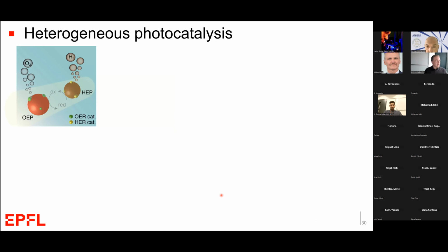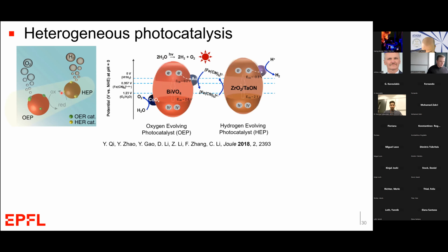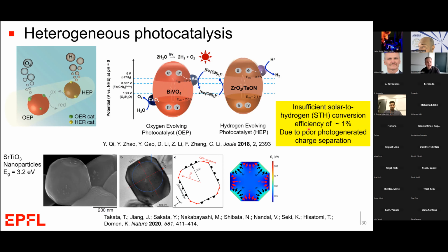And if I switch gears a little bit and talk for a second about that photocatalyst type approach, as I mentioned before, I'm really inspired by this approach, given its simplicity, right? Simply taking a nanoparticle dispersion and putting it into water in a plastic bag or a pond out in the desert and producing hydrogen really with a technical ease. But today, like I said, the performance of these systems isn't so good. And for example, here's a Z scheme, bismuth vanadate, tantalum oxynitride scheme, which only gives about 1% solar to hydrogen conversion efficiency. And it's really due to the poor charge separation.